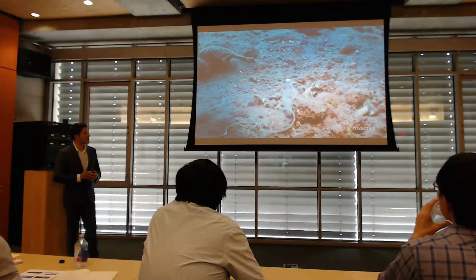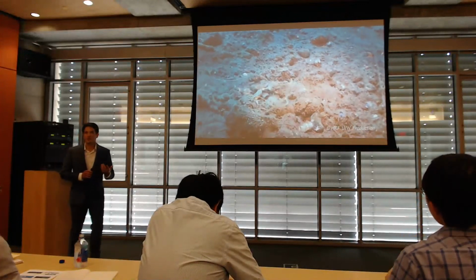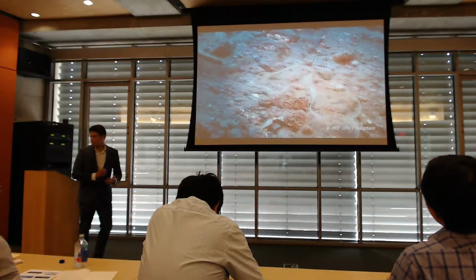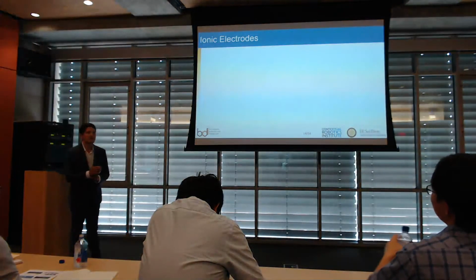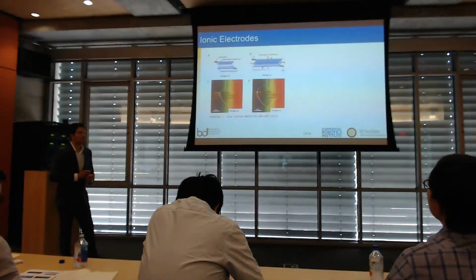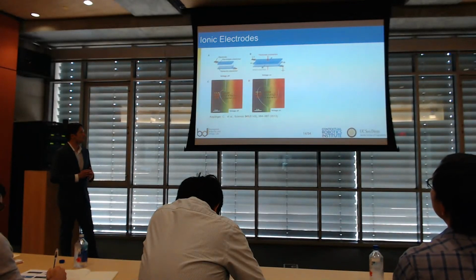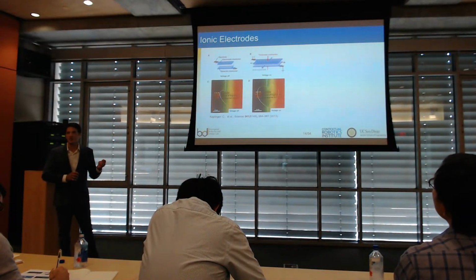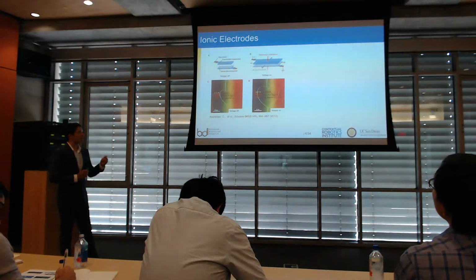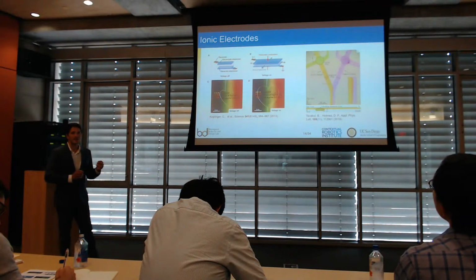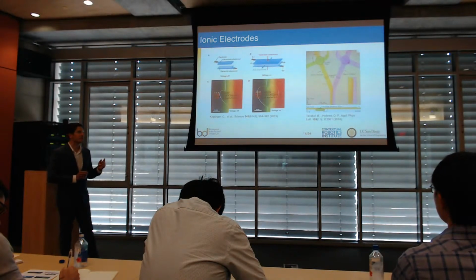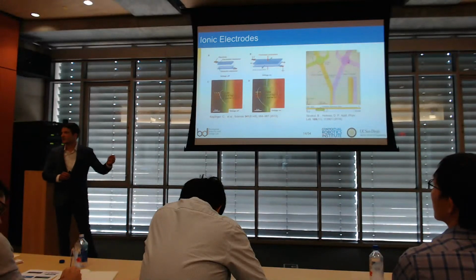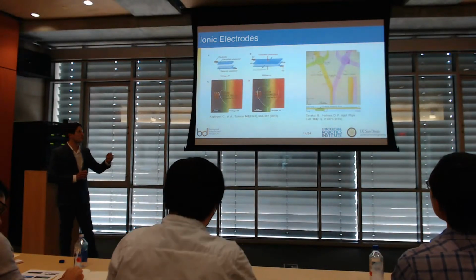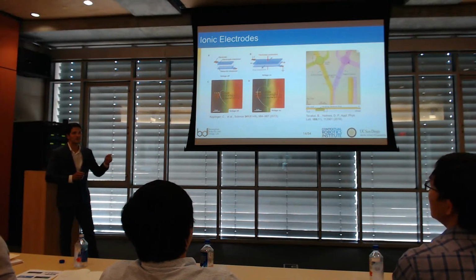So we wanted to see if we could actually make a soft robot that would be transparent like the eel. One way of doing that is, instead of using carbon electrodes, we use ionic electrodes. This example from Harvard uses an ionic hydrogel to show that you could get high-speed actuation with ionic hydrogels. Another group used water as the electrode in a microfluidic strip, so they use water to apply the electricity to the microfluidic strip. But up until now, nobody's used water as electrodes in a robot.